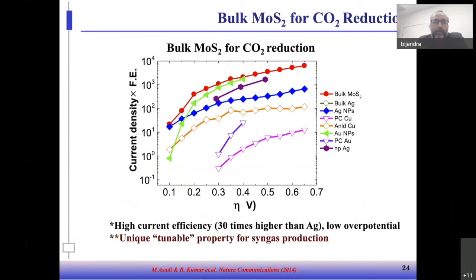So when we try to calculate how efficient they are in comparison to other catalysts, we compare the result with a gold nanoparticle or copper nanoparticle or silver nanoparticle. So this bulk MoS2 shows higher performance in comparison to all these noble metal catalysts. So what does it mean? It means we can replace all these noble metal catalysts by TMDCs. Here we just tested the bulk MoS2.